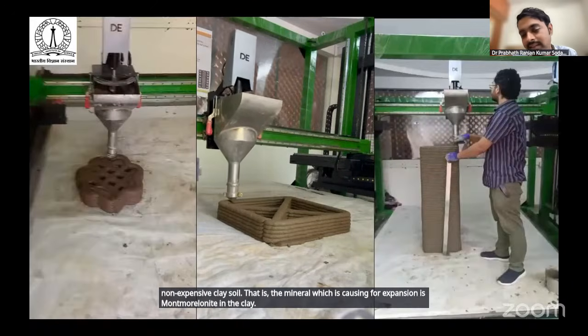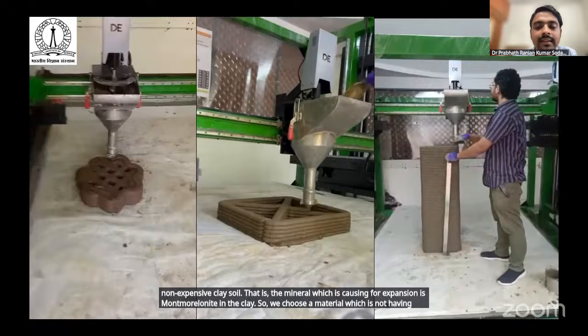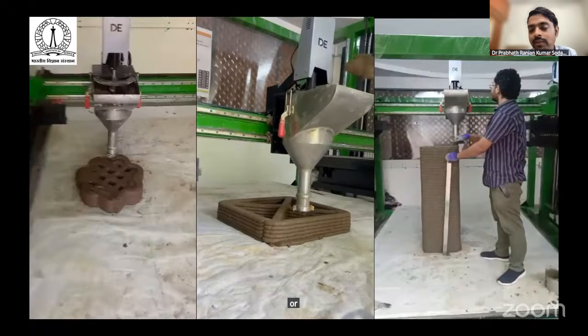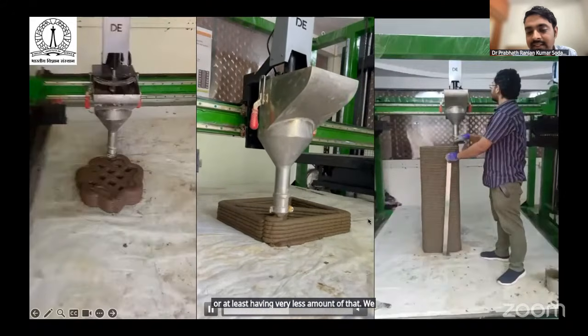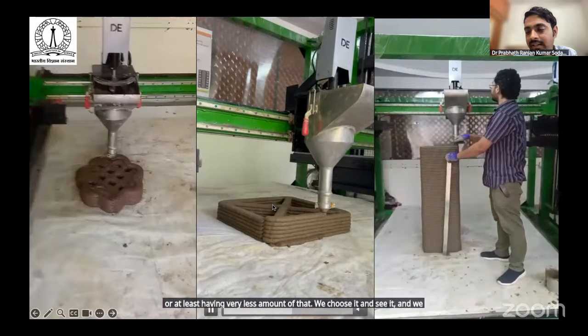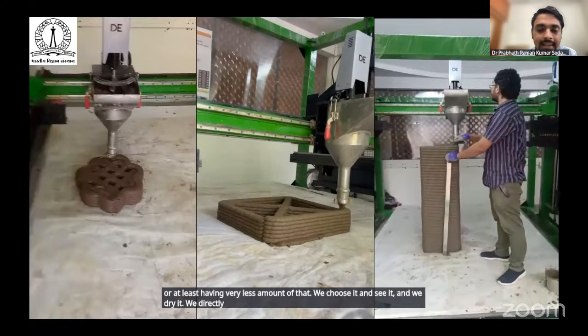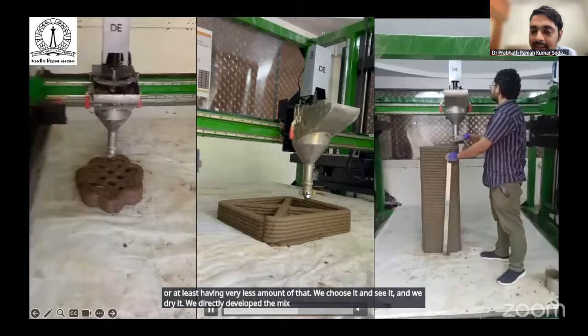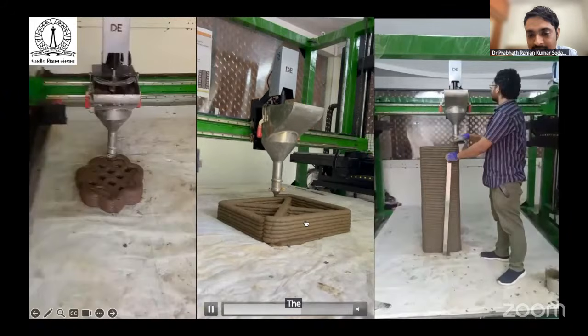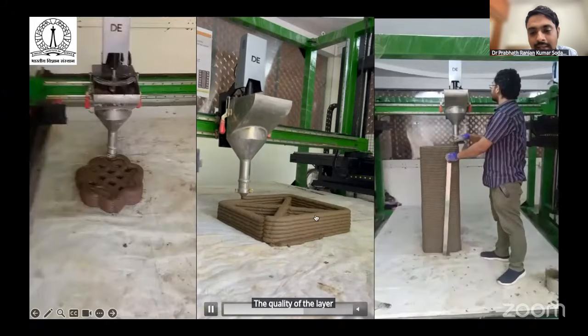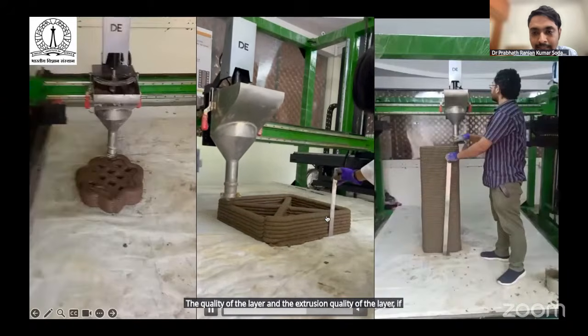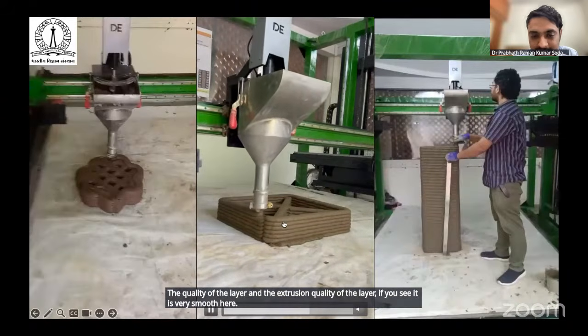So we choose a material which does not have montmorillonite, or at least has very little of it. We choose it, sieve it, and dry it. We directly developed the mixed formulations and started printing. If you see the quality and extrusion quality of the layer, it is very smooth here, and it's very easy to print.